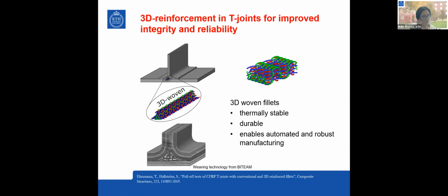Considering shape distortions and geometrical tolerances, we actually have a not automated, but very promising textile technique at KTH. It is a 3D weaving loom, which can produce 3D textiles in almost any geometry. It's totally integrated, all the fibers. You can go from 2D to 3D in one weaving setup. So it's very flexible.